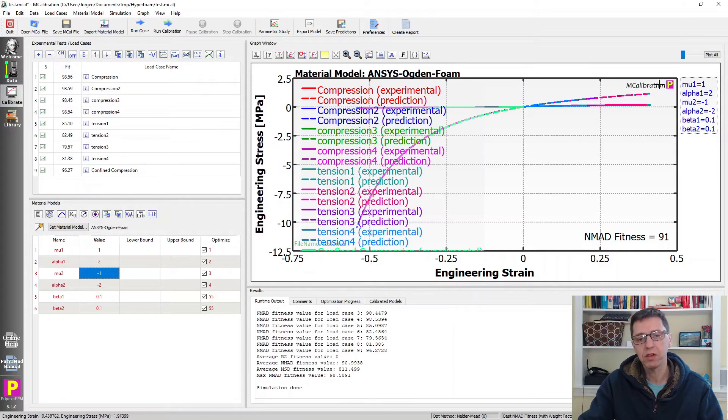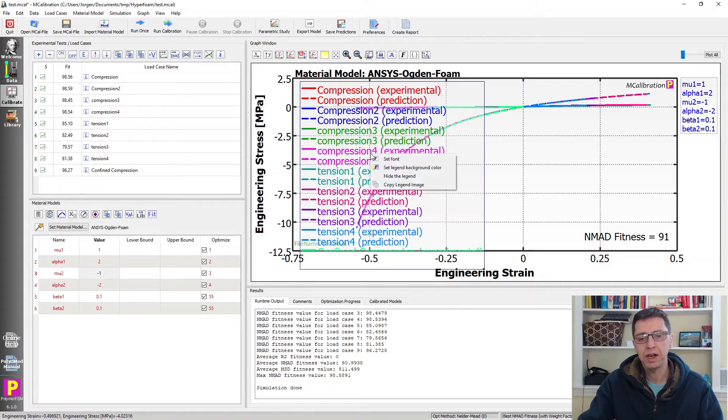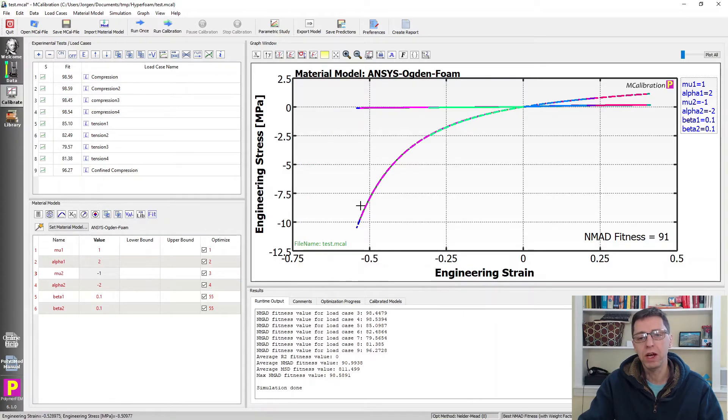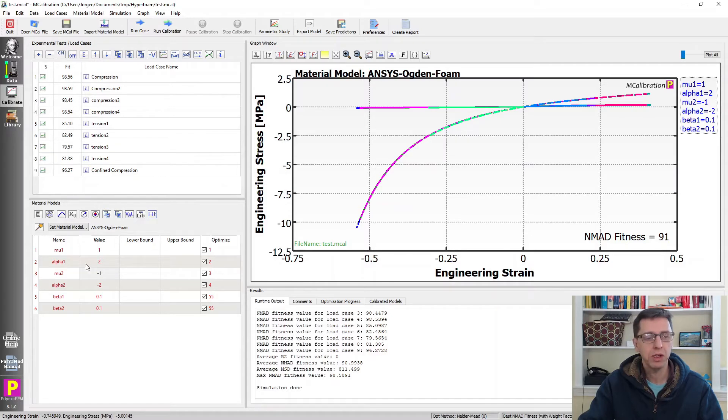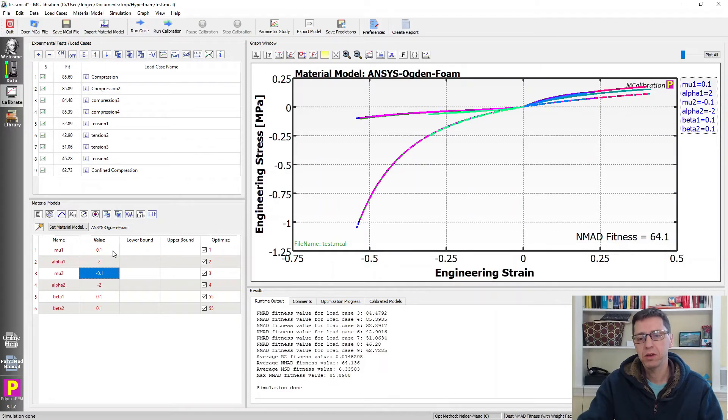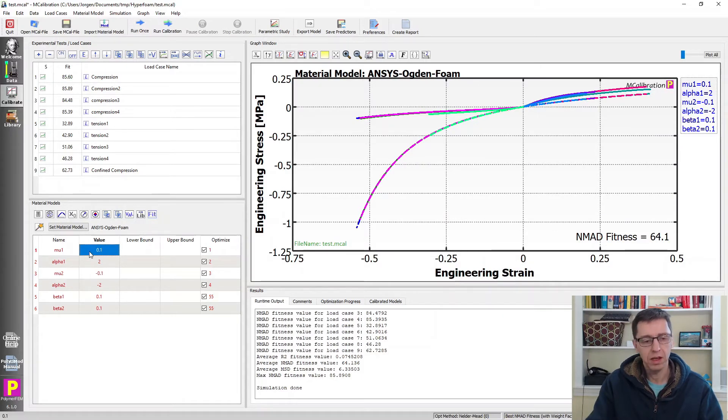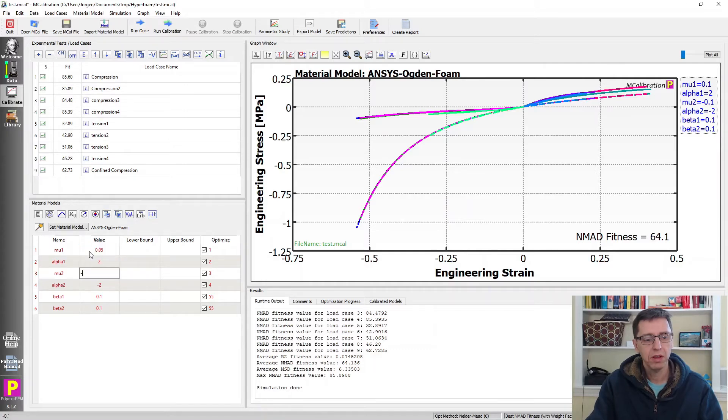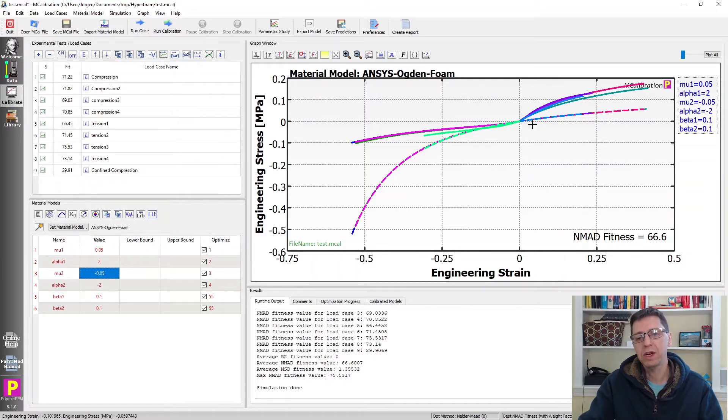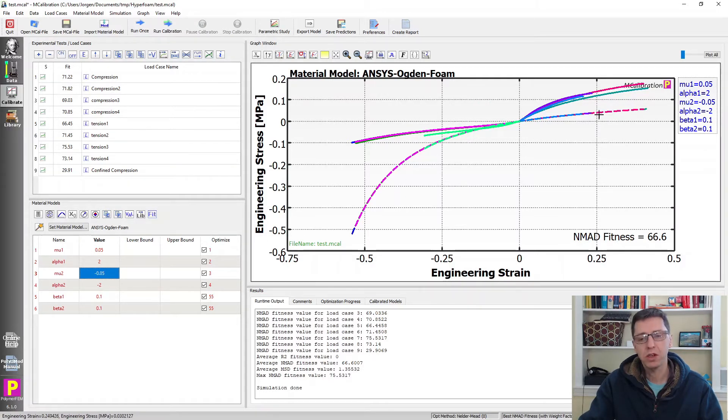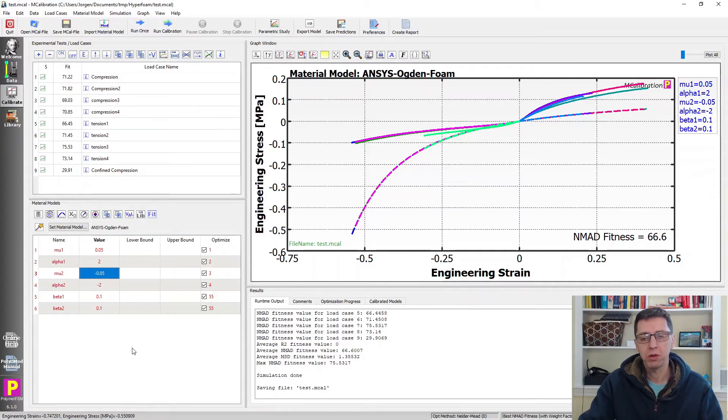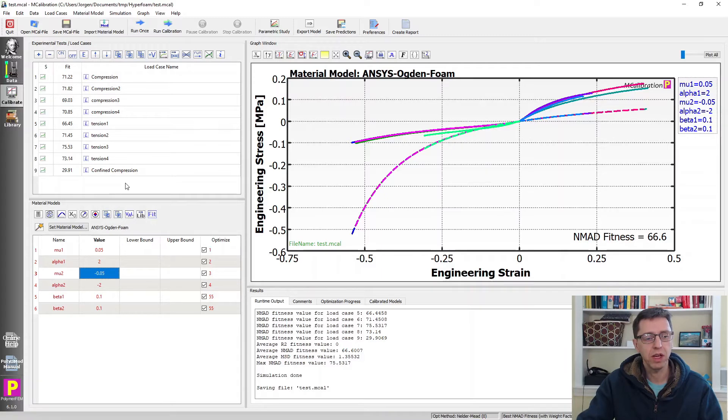I run this once and we'll see that this is the prediction here. I'm going to hide the legend because it's so big. The predicted stiffness is too high. So the dotted line here is the prediction. So we're going to make these 10 times smaller. It's still too stiff. So we'll make this even smaller, 0.05, minus 0.05. Run it again. And now we're starting to see the problem, right? In tension, this model is too soft and compression is too stiff. So we may not be able to fully calibrate them all to this that works really well. But we can try.